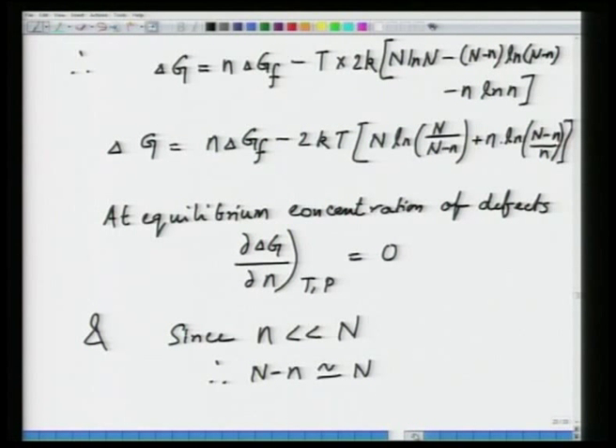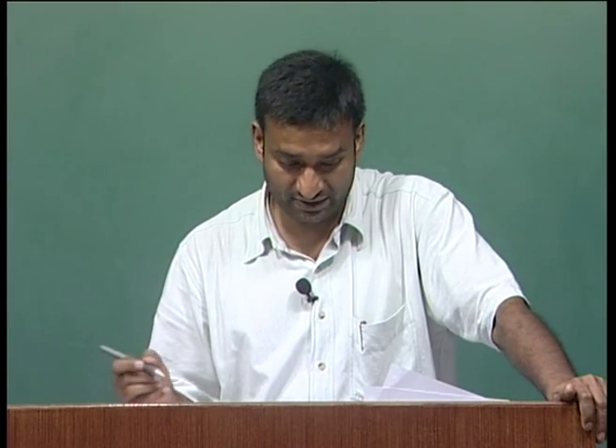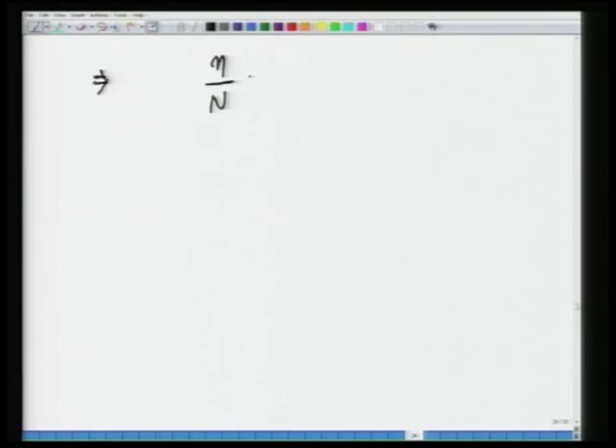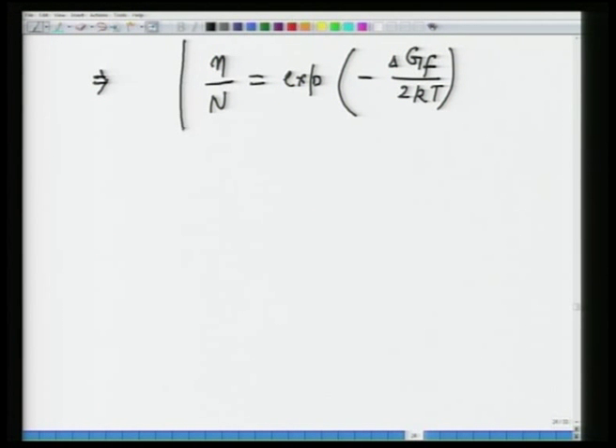So, when you differentiate, what you will find is this. If you do that exercise and replace capital N minus small n to be almost equal to capital N, then you will find small n. So, if we differentiate the free energy equation with respect to n, it's a very simple differentiation, and this would lead to exponential of minus delta Gf divided by 2kT. So, this is an important expression.